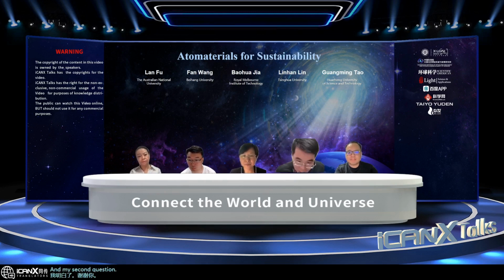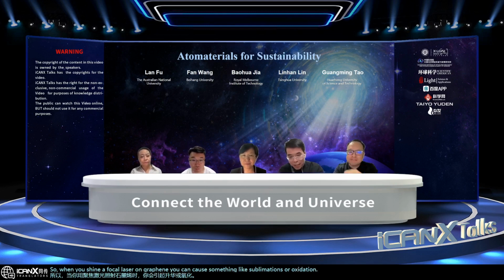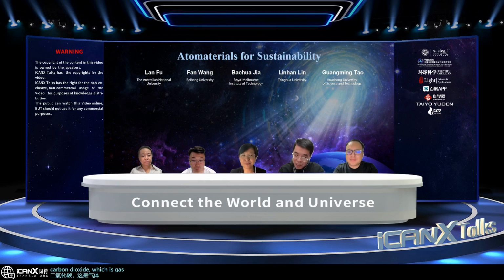And my second question is on the laser reduced graphene oxide. So basically, you shine the laser on the graphene oxide to reduce the material. But as far as I know, laser can also oxidize graphene. So when you shine a focal laser on graphene, you can cause something like sublimation or oxidation. And sometimes you can get carbon monoxide or carbon dioxide, which is gas-based. And on the solid state graphene, sometimes we can also get some graphene oxide. So it seems to me there's a trade-off between the two processes. So is there any trick to control the balance between the two processes?